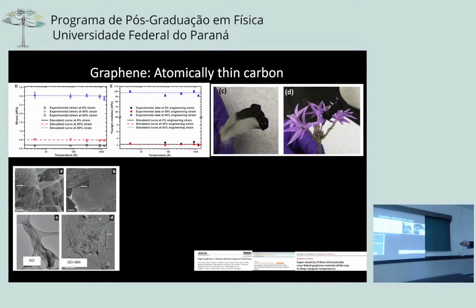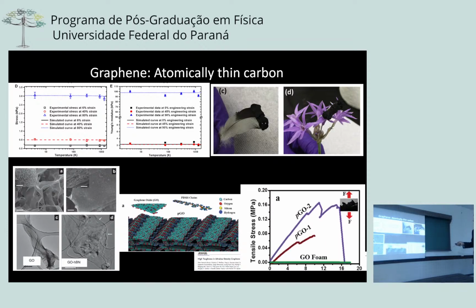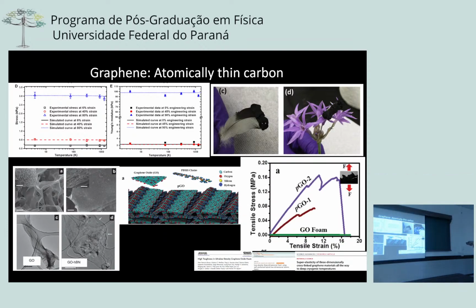Also, being a 2D material, when I say 2D material, what it means is, if this is the graphene oxide, if it is alone or standalone, it can wrinkle, it can bend and so on. But if I take another 2D material, hexagonal boron nitride, we can modify the structure. So what you see here folded and crumpled can be made flat by just putting another 2D material. That opens a lot of opportunity, because what we have in graphene is surface and edge, right? Now if you can start combining with different materials and modify its basic structure, you can build all sorts of interesting structures.